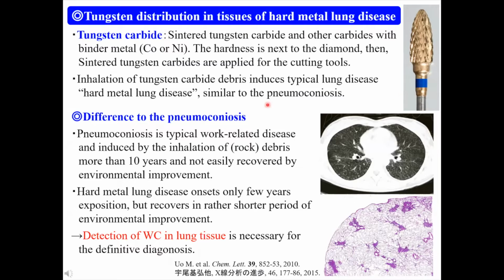Inhalation of tungsten carbide debris induces a typical lung disease called hard metal lung disease, which is similar to pneumoconiosis. For the definitive diagnosis of this lung disease, the detection of tungsten carbide, the causative material, is important. But the inhaled amount of tungsten carbide is quite small, therefore it was not easy with the conventional method. Therefore, we applied the synchrotron radiation XRF.